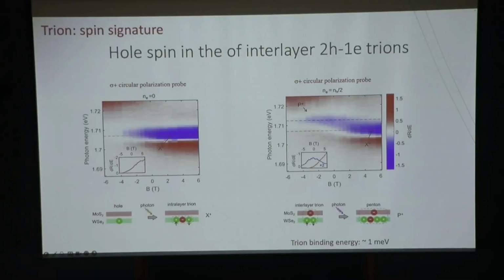Now let's look at the new peak and see how it changes with magnetic field. What you can see is that at the low field region, it's symmetric between positive and negative field, and close to 0, it's not changing much. That's a hallmark of the trion, because a trion requires the 2 holes to form a spin singlet. And if you have a spin singlet, of course, it doesn't respond to magnetic field. You cannot change the overall spin of the holes.